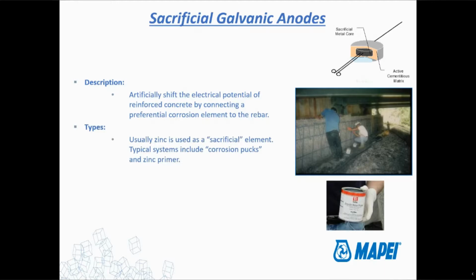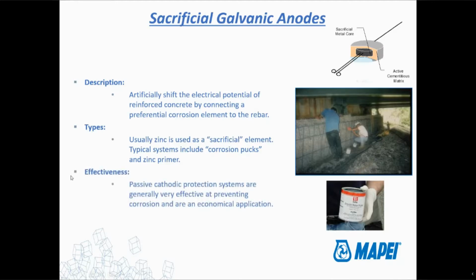And if you have an anode with, say, a 10 to 15 year service life, the thought is by the time that anode fully consumes itself, the concrete that it's in will have absorbed some chlorides. It will have dropped in pH. It'll be more at a balanced state with all of the concrete around it. And then you don't get that chasing the repair situation. So very, very effective. They definitely work. There's plenty of science out there that proves that it works.